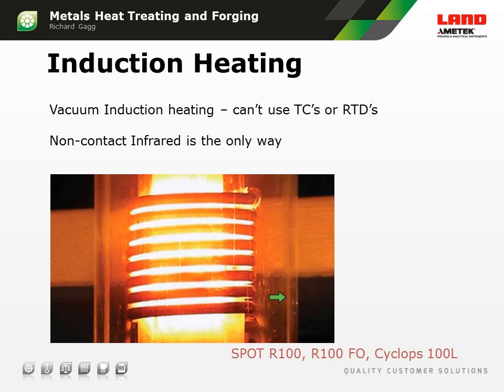So again, a ratio thermometer is ideal for this because the ratio thermometer can see through the quartz without any interference at all. And then it can see a partially filled target and give an accurate temperature measurement. So again, things like the Spot R100 or the R100 fiber optic, or again, with a Cyclops 100L, focused very short between the gaps in the coil.